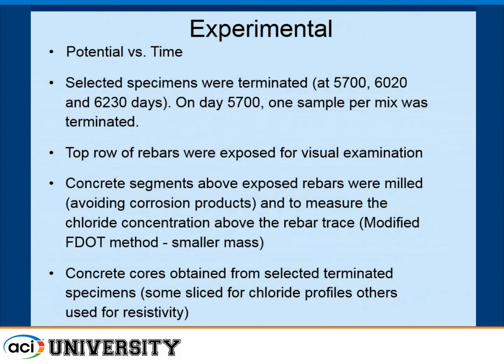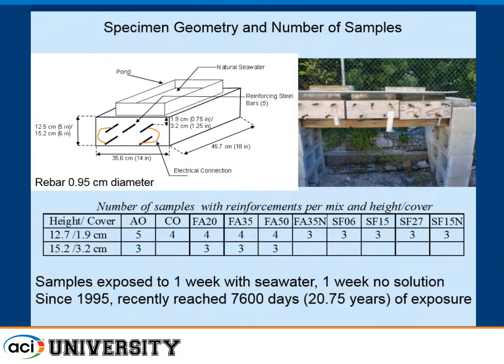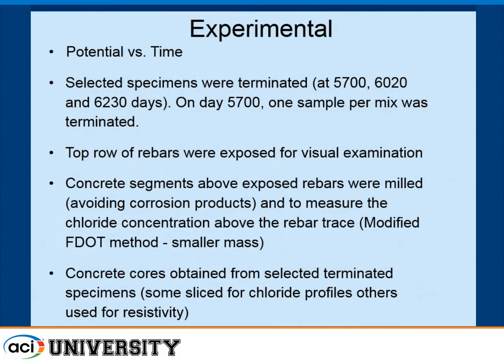Some of the measurements that were performed were potential versus time of each one of the rebars. I forgot to mention, there were actually 5 rebars, and 2 pairs were interconnected, whereas the middle one was not. And then we terminated specimens at 5,700 days, 6,000, and 6,200 days. At 5,700 days, we terminated 1 specimen per type of mix.